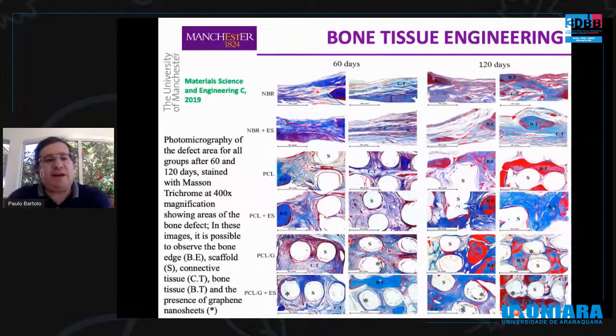And this was also confirmed with photomicrography images, in this case stained with Masson's trichrome. In this case, the blue dye identifies the connective tissue and also primary mineralized bone, depending on the intensity of the color, while the red dye corresponds to mineralized bone. So again, the results show that in the case of electroactive scaffolds with electrical stimulation, the amount of new bone formed is higher and the bone is much more organized. The small tiny black dots in the PCL graphene scaffolds correspond to graphene, and these blue-red zones, this mix of blue and red zones, correspond to tissue maturation.